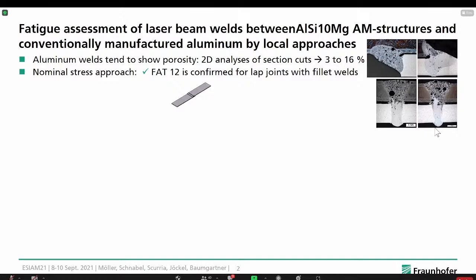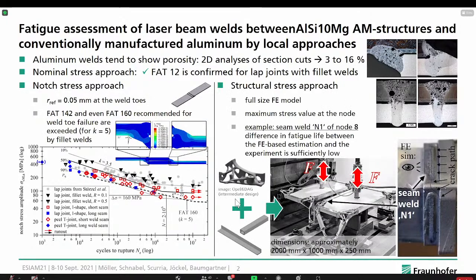Yes. Okay. We got a question from Mr. Sprengel. He has asked, what happens if you flip around the stacking sequence? Let's say you have done the welding with the AM part on top, the overlapping part. Does it make any change if you change the sequence? Yeah, we also made some trials on this, and we have seen that we got more problems when flipping it around, since the conventional 6082 material is not too easy to weld, so we struggle with this material when we flip it around. So this was the more practical choice in this case. So we have more tendency to have cracks in the conventional material. Okay. Yeah. Thank you.